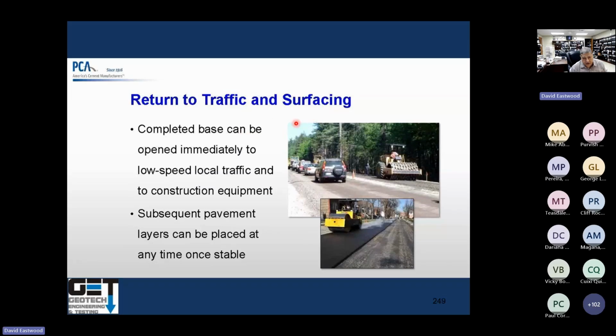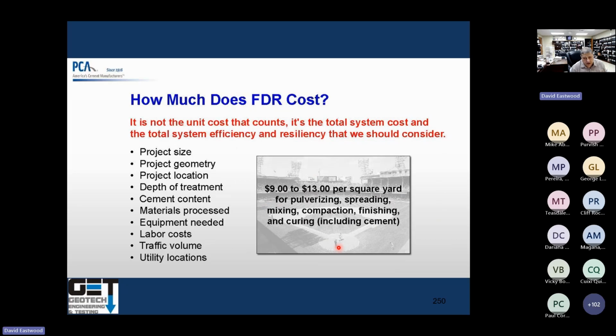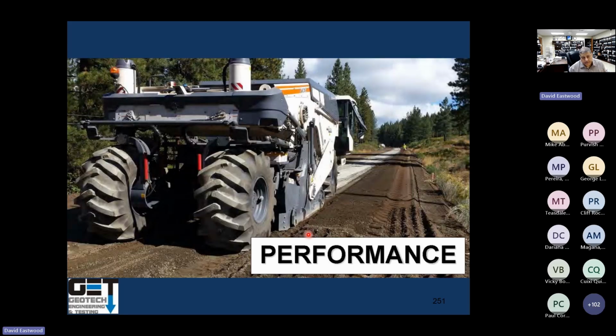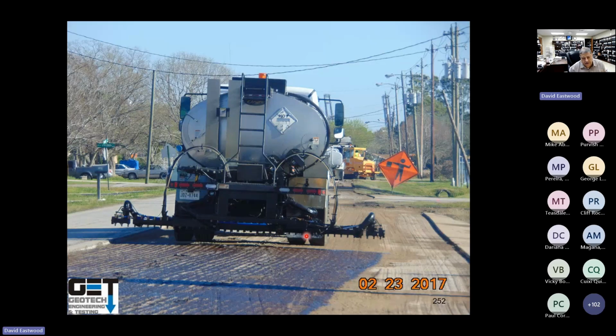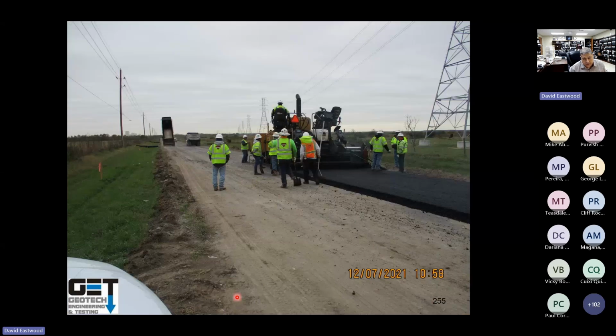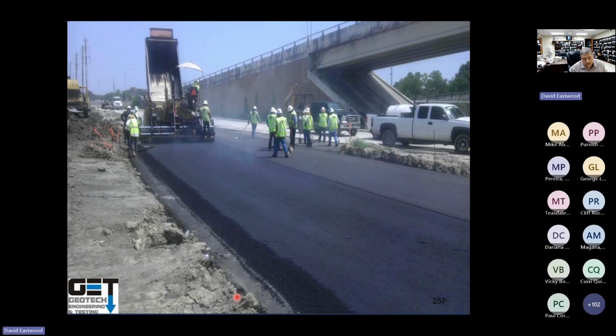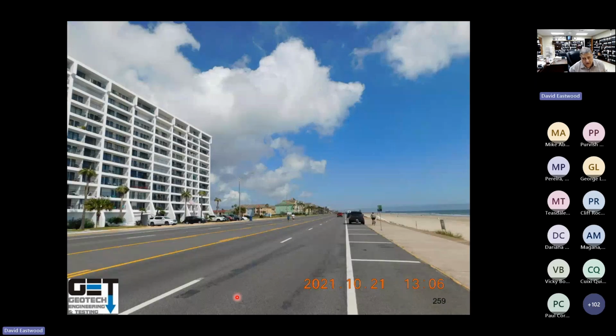Then you turn it to traffic. You can complete it and turn it to traffic immediately and put the asphalt course on top of it later, or you can do it right away. You put a tack coat, and then you put the asphalt surface course on top of it. The cost a couple years ago ran about $9 to $13 per square yard for mixing, compaction, and finishing. Basically, after you stabilize that subgrade for full depth reclamation, you go in there and put a tack coat in, you bring in your asphalt, and lay it on there. You compact it.